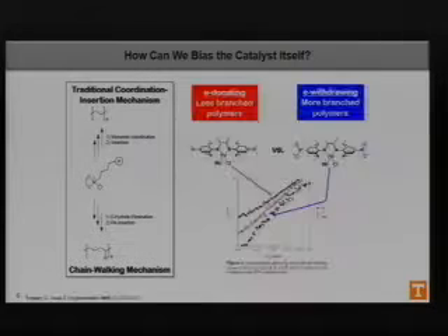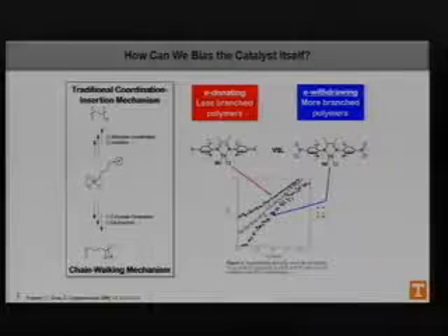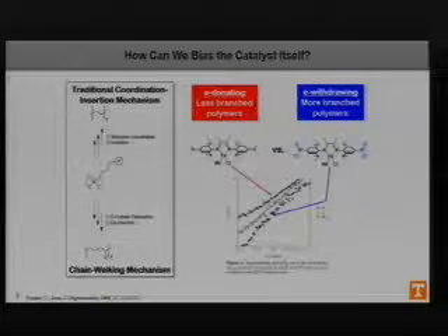And in our lab, we wanted to know if there was a way that we could actually bias the catalyst itself to prefer either this mechanism that would lead towards more linear, more rigid polymer, or if we could bias it towards the chain walking mechanism. Now, we drew inspiration from a report in 2005 by Guan and coworkers, where they showed that if you put electron donating groups on the pendant aryl rings of these palladium alpha diimines, or electron withdrawing groups, such as the nitro groups here, you can essentially perform the same sort of control in which you create more or less branching. Now, this was a very interesting report, but having to synthesize a discrete catalyst each time you wanted to synthesize a type of polymer isn't exactly ideal.